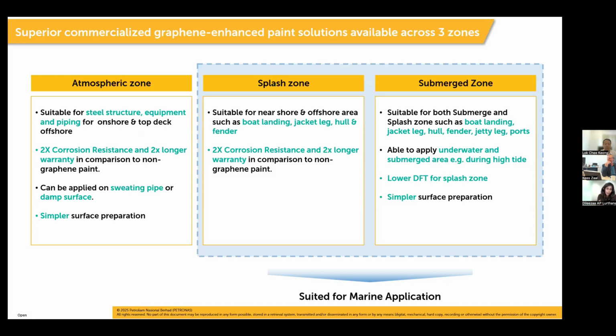And the most interesting part that seems to be gaining traction among our asset users is that it requires simpler surface preparation. One of the biggest challenges that the team has is the fact that in an oil and gas environment, you would have to do extensive surface preparation before you paint any system on the metal or steel substrate. But with graphene in it, and the fact that graphene has better adhesion quality, we can now explore the possibility of having simpler surface prep, and that makes application a lot easier and exciting, and not to mention more effective and productive.